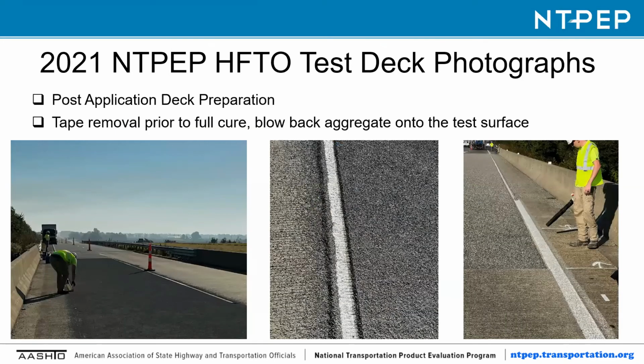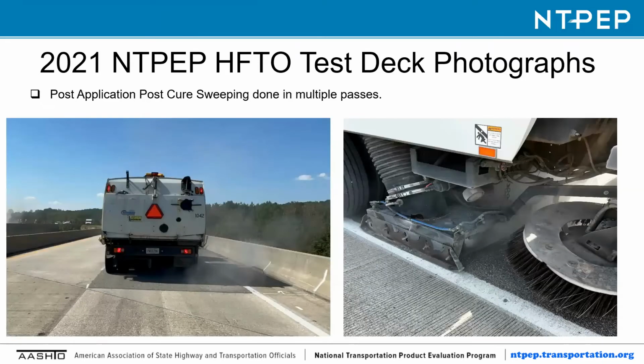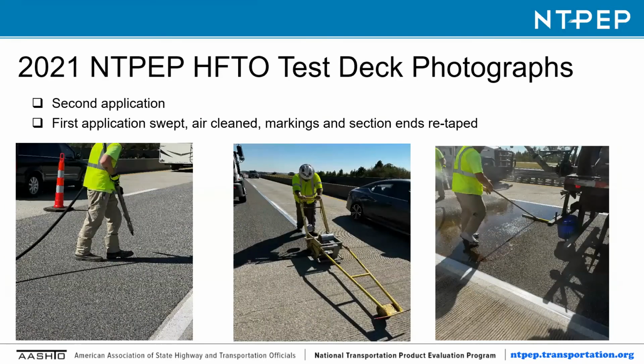Post-application deck preparation, of course, they pull the tape up before it sticks too bad, and you do not want to let that happen. After the tape's removed, they blow the aggregate on top, then come through with a sweeper or a broom of some type to remove the excess aggregate. On bridge decks, the second application, they usually do an air wash. Then they go right back on top. They put the tape back out and they start their second application.